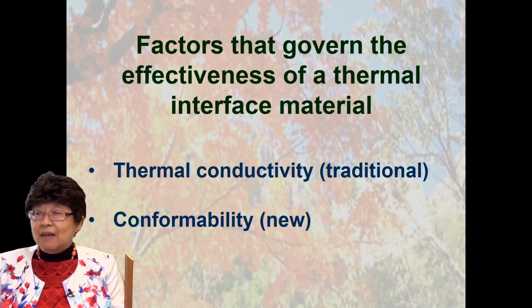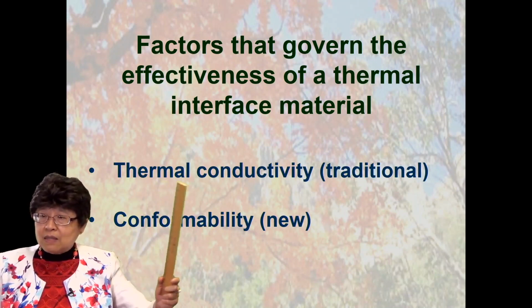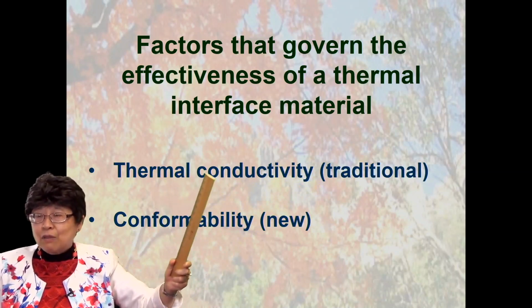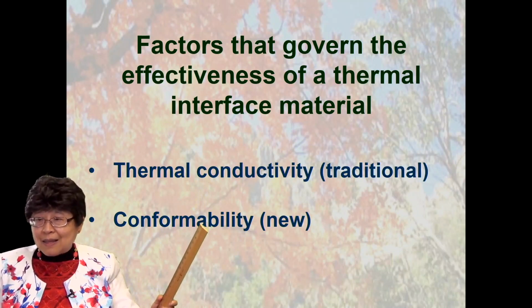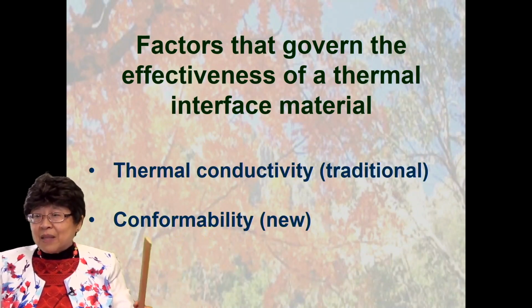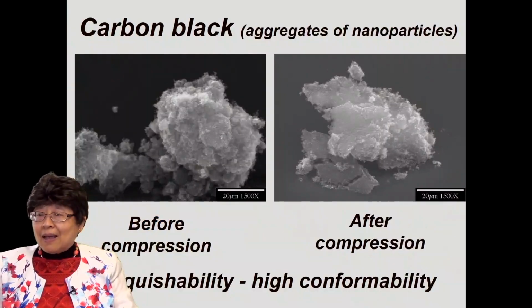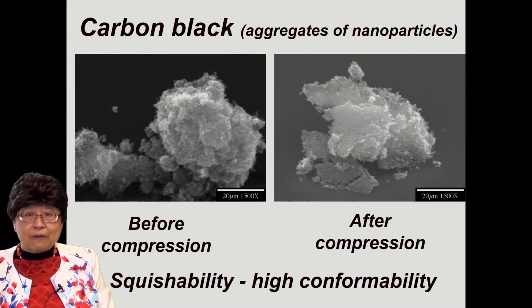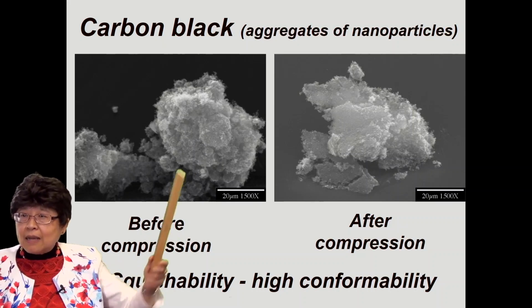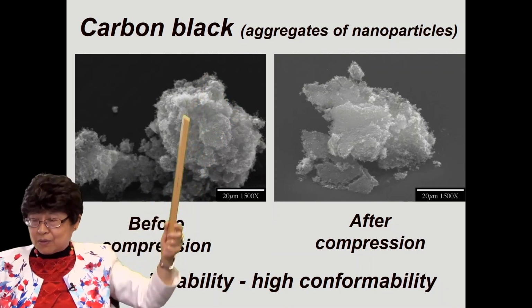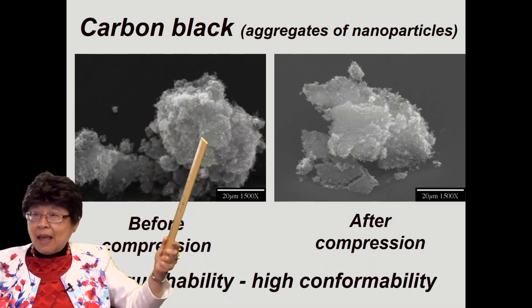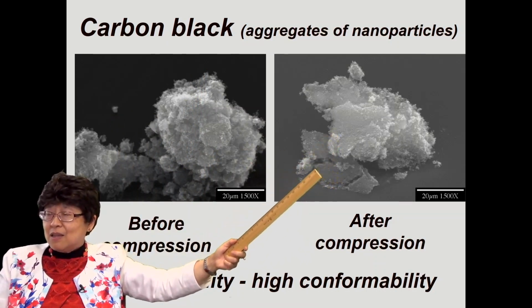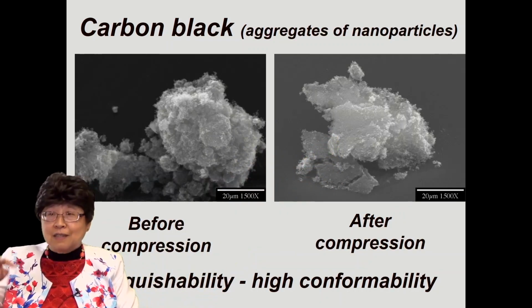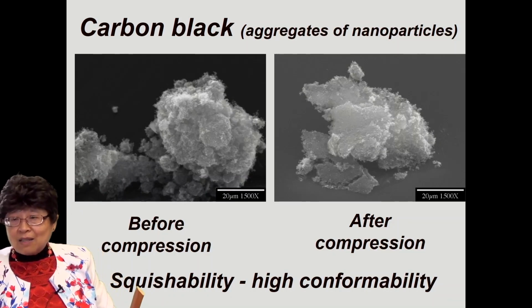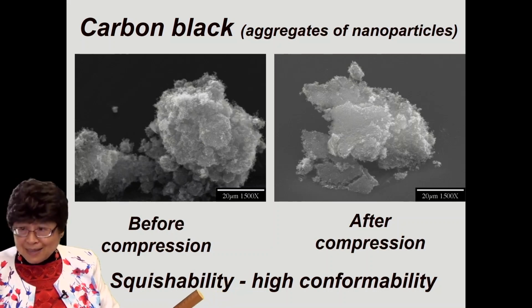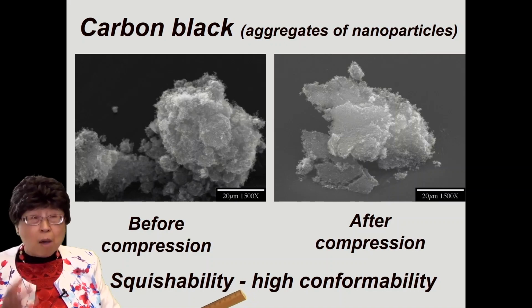So these are the two factors that govern the effectiveness of a thermal interface material. One is the traditional factor, which everybody knows: the thermal conductivity. But a factor that people didn't realize until I put forth that concept back in around 2003 is the importance of conformability. And it turns out that carbon black is very, very conformable because it is in the form of aggregates of nanoparticles. And so you can compress it a little bit and it squishes down. So it conforms to the shape of whatever surface that you're pushing into it. I call it squishability, which means compressibility, and that results in high conformability of the carbon black solid.